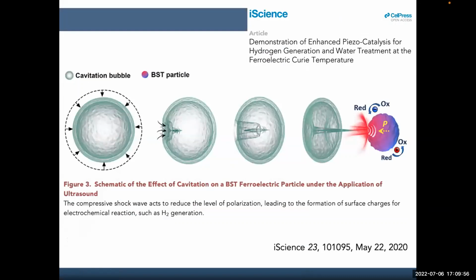I think with mechanical deformation, it tends to be relatively low frequency. So a lot of the work on piezo-catalysis tends to be the application of ultrasound, and that's because it's much higher frequencies, 40 kilohertz, for example, a much higher intensity. Remember, it's the change in polarization that develops the charge. So if you increase the frequency of the oscillation, then you're going to develop larger charge, and the inherent cavitation effects that you get within the application of ultrasound mean that as the bubble collapses, that bubble collapse will produce very high pressures and also very high temperatures. So you're going to get much more significant changes in the polarization of the material, piezo or pyroelectric effects.